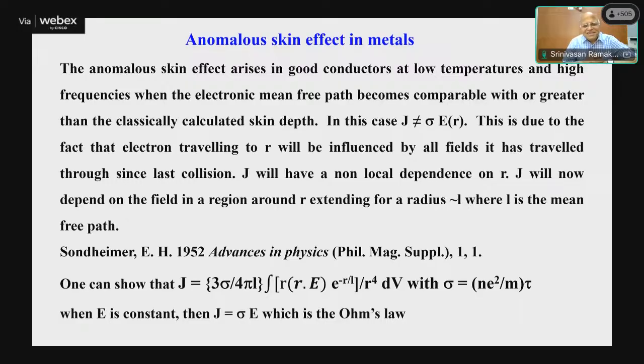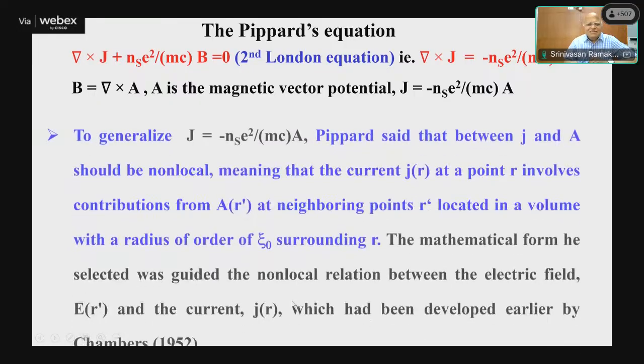So what he did was, this is an anomalous skin effect which we have studied in good conductors. What happens is that when the mean free path compares with the classical skin depth, J will not be equal to sigma E of r. This is because the electron traveling up to the distance r will be influenced by all fields it has traveled through since its last collision. So J will have a non-local dependence on r. This was done by Sondheimer in 1952. He suggested that J is given by this expression, which will go to Ohm's law when E becomes a constant. So he took this analogy and then wrote an expression.